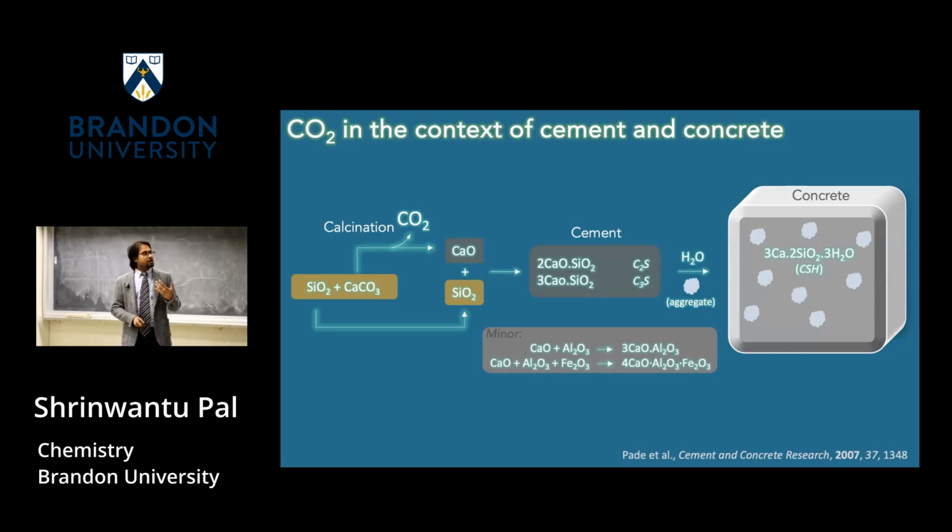As the cement undergoes the hydration reaction, you're basically generating a new mineral that is calcium silicate hydrate, called CSH in the concrete industry. This is a 3D network of calcium silicate and water that embeds all the aggregates inside to form your precast concrete block. So you should realize that cement and concrete are not the same thing. Cement is just a binder which undergoes hydration reactions together with aggregates to form this 3D structured block, depending on the size of your mold, and you get your concrete block.